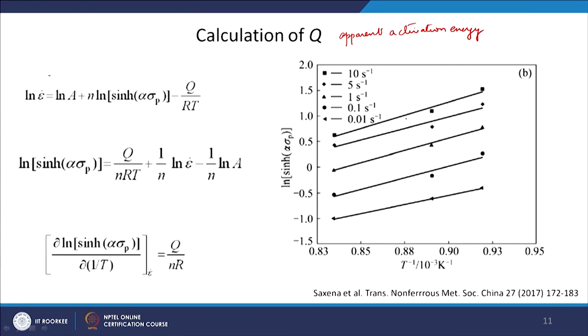Also, if you remember, we saw some flow stress curves where at low temperature it shows strain hardening, then at some intermediate temperature it shows dynamic recovery, and at even higher temperature it shows dynamic recrystallization. So, steady state, sometimes softening, and so on. The idea is that the microstructure is continuously changing, it is dynamic. So, when we calculate the activation energy from the data of different temperatures, the activation energy you get is going to be an apparent activation energy.